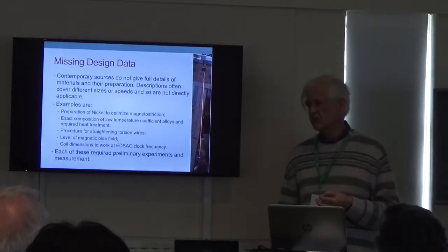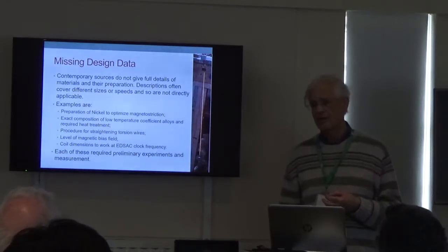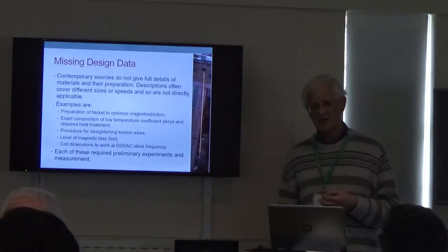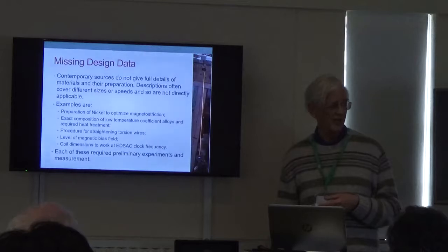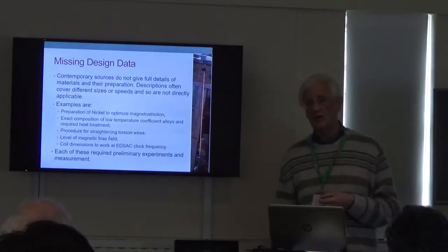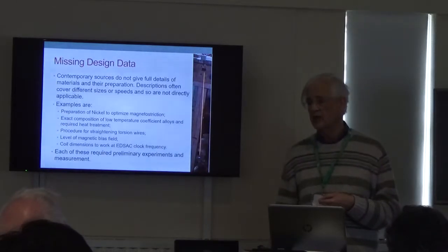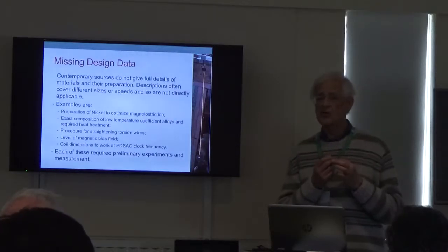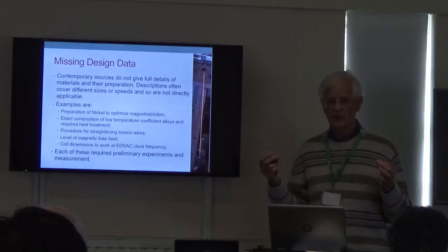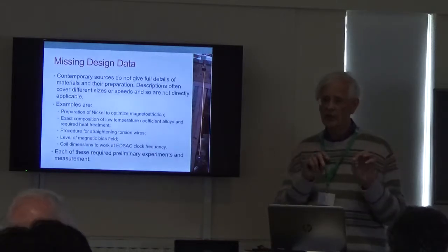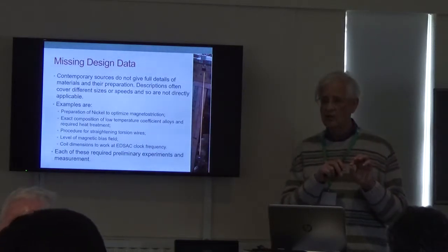We had to find a procedure for straightening 3 metre lengths of wire. If you want to get a clean spiral out of it without any kinks or possibly even places where the turns touch, you have to start off with a nice straight length. It turns out you have to start with the wire straight, not pre-curved, because bending the wire into a spiral produces a dispersion effect.